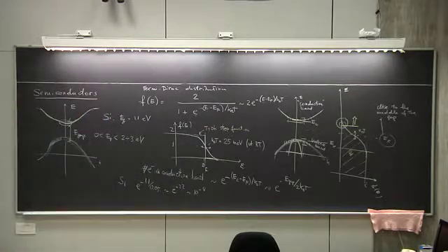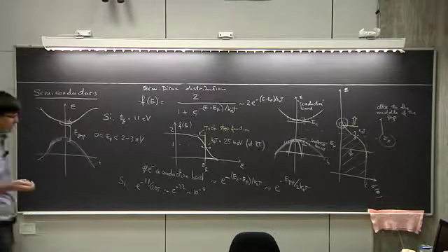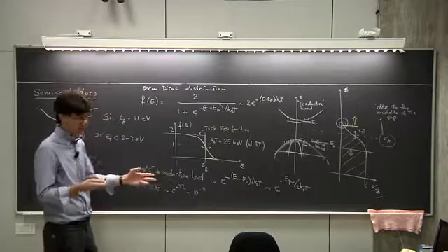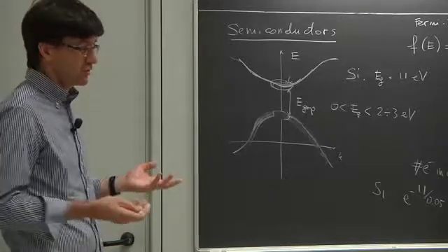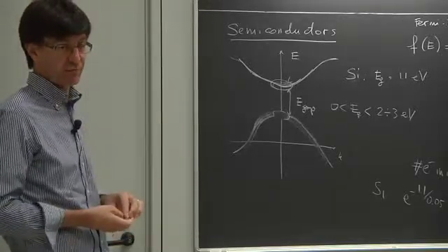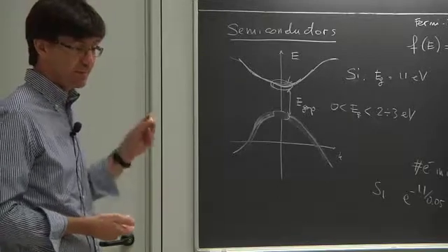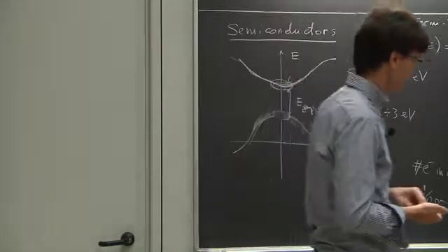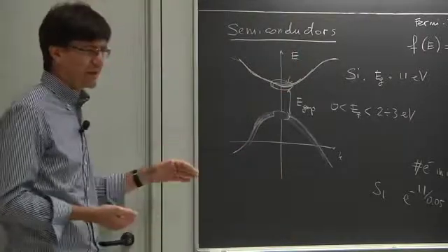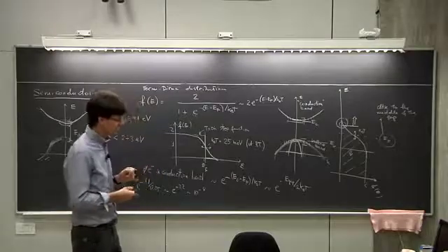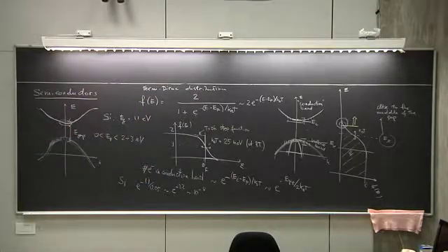So by changing the temperature by 30 degrees only, I've been able to change the number of carriers, the number of electrons that I have excited here thermally, by 1 order of magnitude. That means also the conductivity of the system has increased by an order of magnitude, just by changing the temperature by 10%, 30 centigrades. So the resistivity of a system like this, even though it's extremely high, conductivity extremely low because there's no number of carriers, is extremely sensitive to temperature. So small changes of temperature can change the conductivity by orders of magnitude, which is one important property.